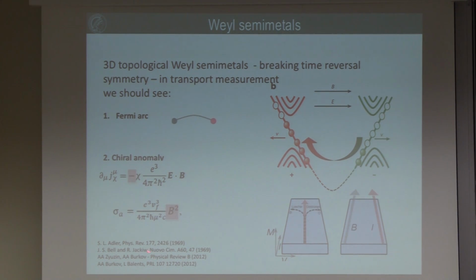So what do you expect for Weyl quasi-particles or fermions? One thing I already explained—we expect a Fermi arc on the surface which connects the Weyl points in the bulk. But due to the very special electronic structure and chirality of the Weyl points, we expect even more properties: in case of a magnetic field parallel to the current, we pump electrons from one Weyl point to the other, and this leads to many properties which we normally see only in magnetic material.